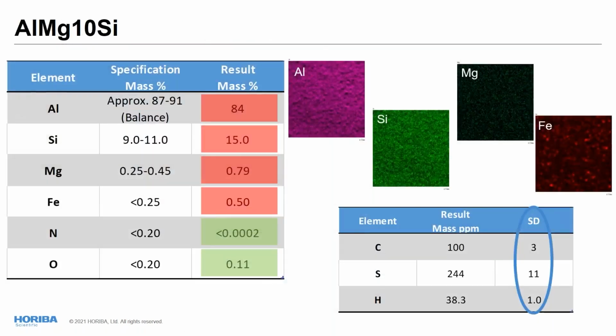Let me show you now some results we obtained on the various samples that were used for additive manufacturing purposes. What you can see here are some results obtained on a fresh aluminum alloy powder, and those are the measurements we did using XRF and the elemental analyzers. And compared to the specification, and you can immediately see, I put them in red, that this powder was not matching the required specification, mainly due to contamination in silicon, but also slightly too high values for magnesium and iron that made the aluminum, that is the balance to 100%, too low compared to the specification.